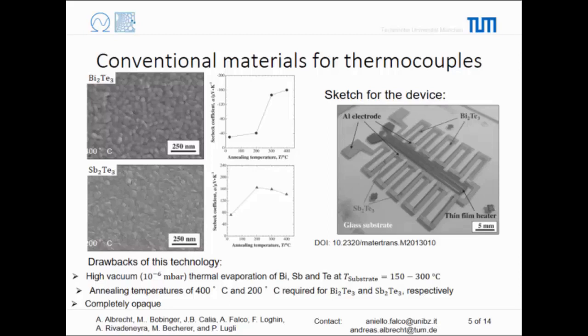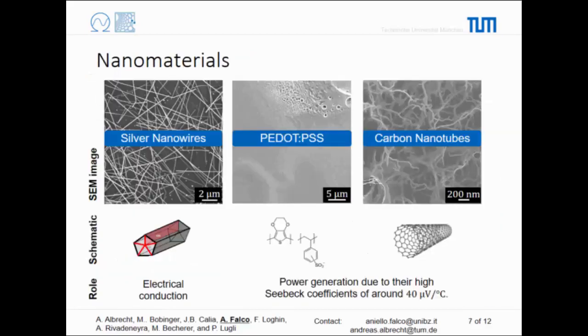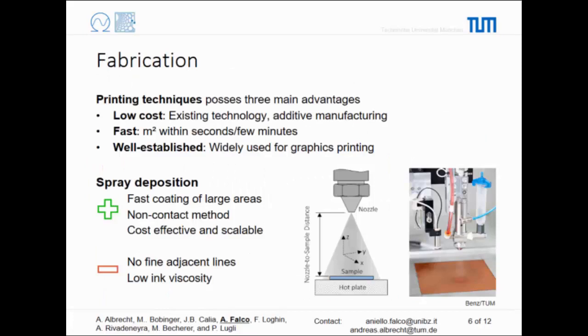We use the simple spray deposition method. There are several ones, and we went for the air-assisted one because we were not looking for particular uniformity of what we were about to have. Spray deposition means that we have a solution. In this solution, we have a dispersion of our material that we want to deposit, and then we use the kinetic energy of air to atomize this material and to direct it towards a substrate.